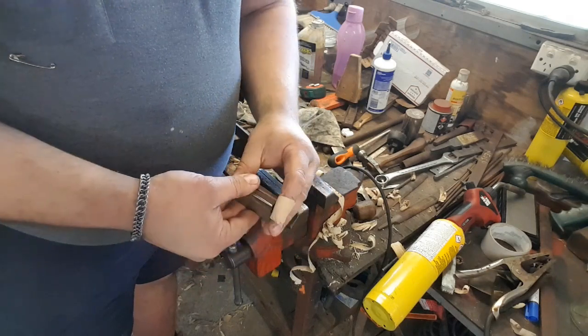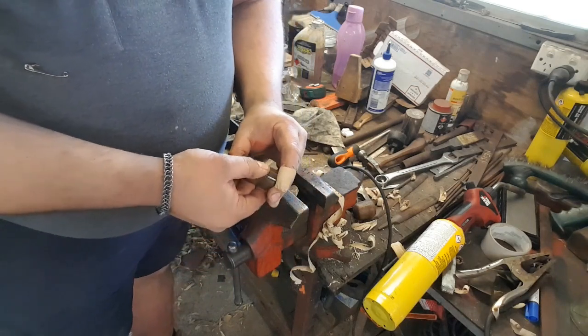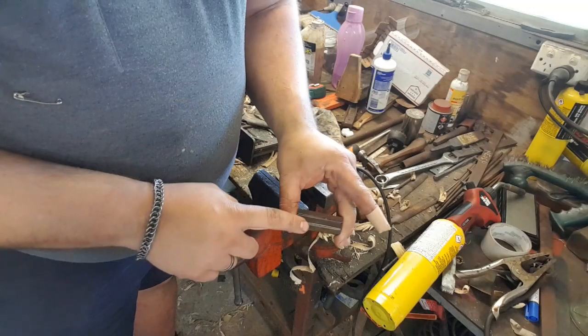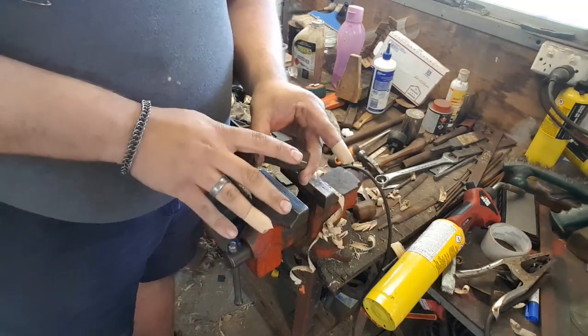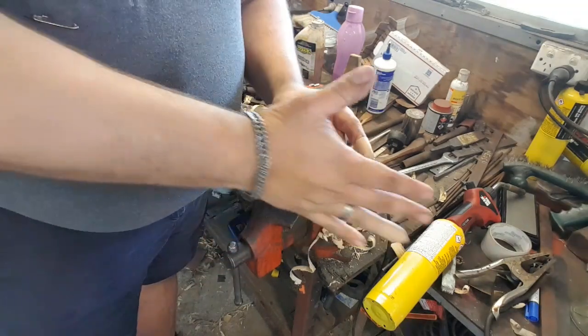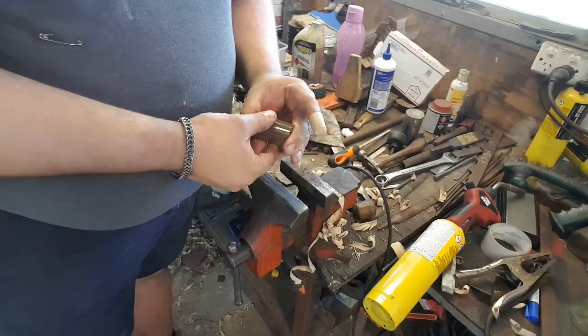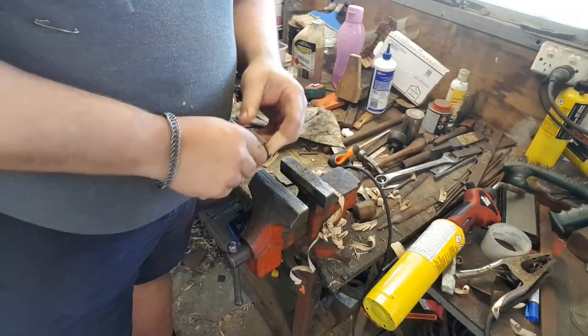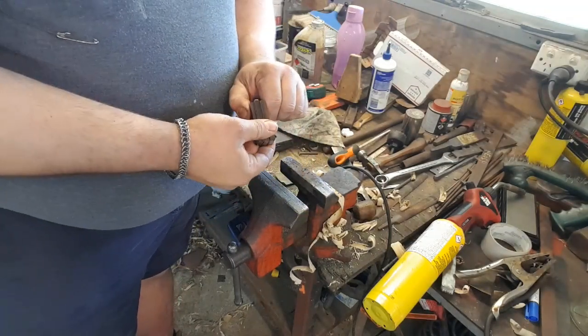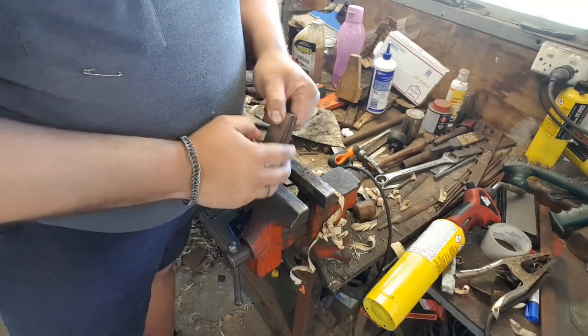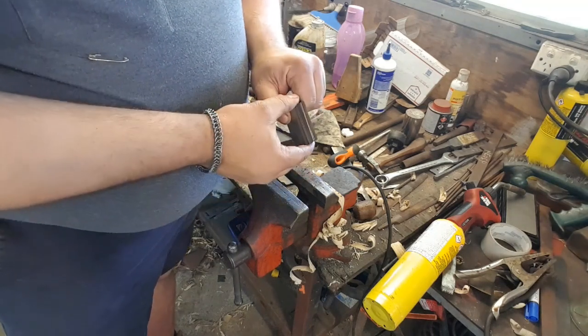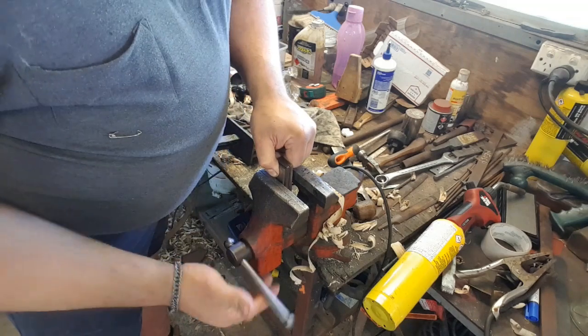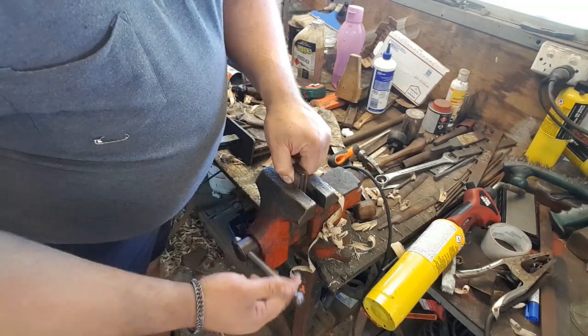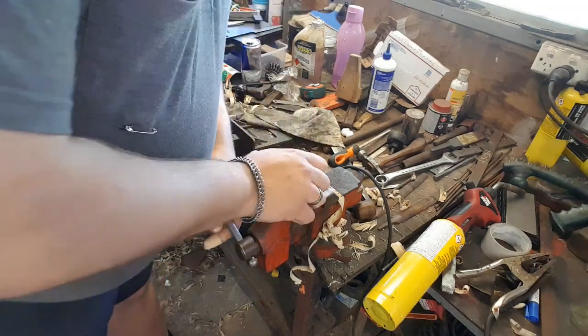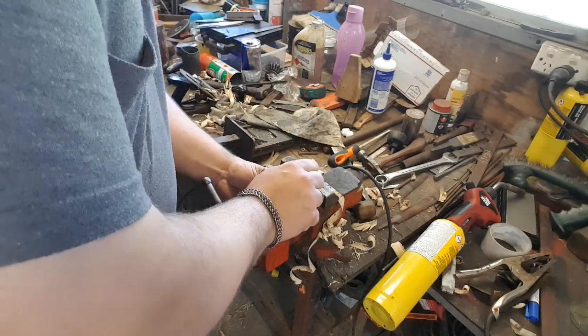Doesn't matter about the outside as well, that's not going to weld. But now that we've got it nice and clean, the bandsaw is slightly bent, and a lot of the time you're going to have slight variations in straightness in your billet. The flatter you can get something, the easier it is going to be to weld. But we can somewhat mitigate that by straightening it up in our fingers and then clamping it in a vise. Or if you don't have a vise, you could use a clamp. Funnily enough, a G-clamp or an F-clamp.